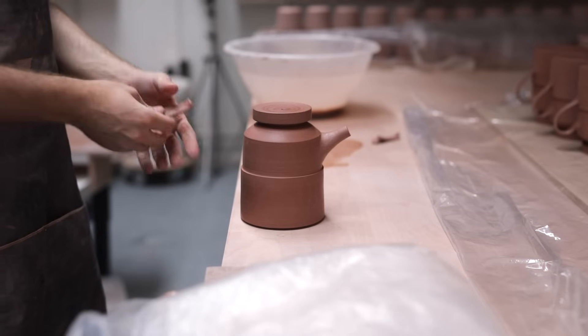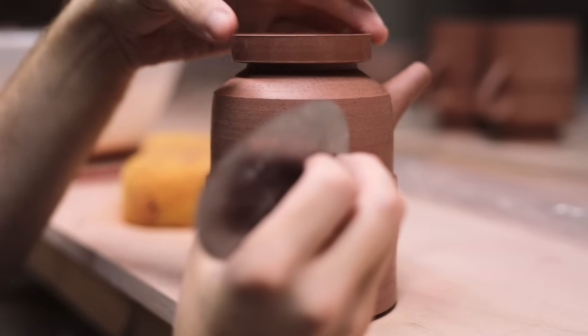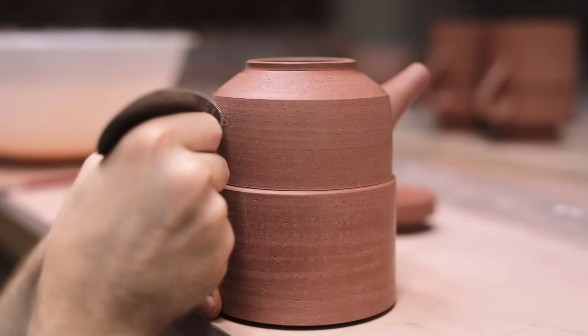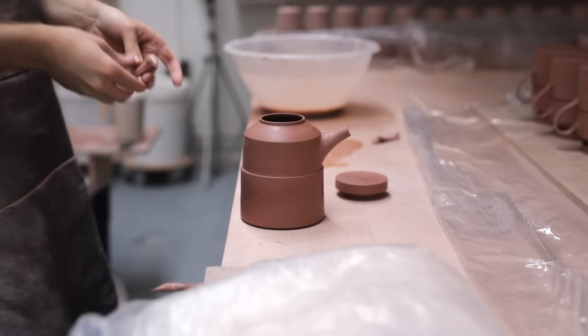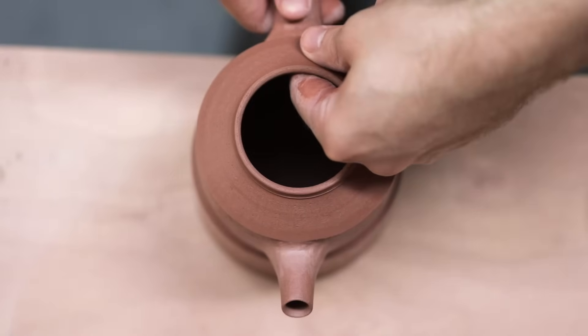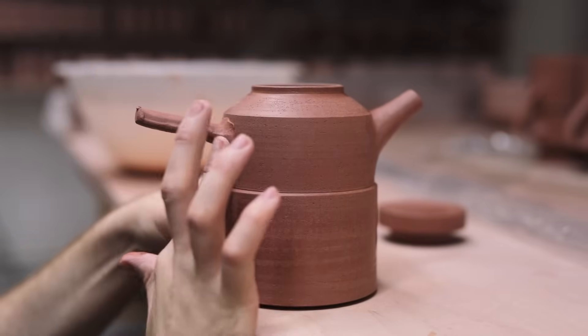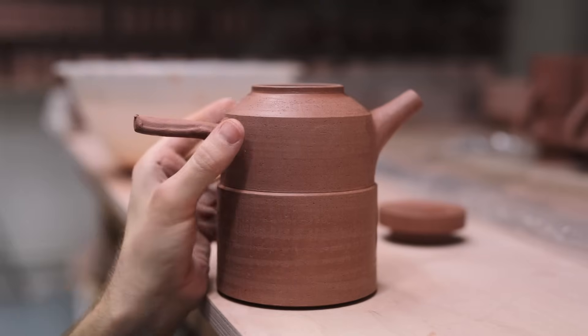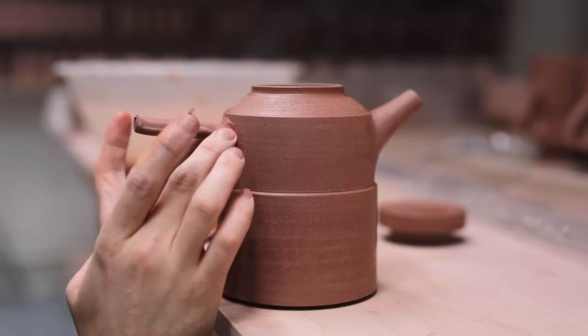So I take one of the blanks and I tap out one end. This creates a flare of clay which I'll easily be able to blend into the body of the teapot, without having to steal material from the length itself, which would create a thin spot in the join. I then use a serrated kidney to score an area that's directly opposite the spout — the two parts really need to be in line — so I crouch down and line them up, and then dab some slip onto the scored area. I then take the handle blank and really firmly push it onto the scored section, and once again there's a hand inside the vessel which braces the pressure from the inside, preventing the handle from deforming the wall as it pushes inward. I then follow up with a dry fingertip that blends in the clay from the tapped-out end of the handle all the way around. This join has to be very secure, as the next stage — when I pull it finer and thinner — can put a lot of strain on the join itself, and if it isn't done sufficiently well enough, there's a good chance the handle will just be torn away from the teapot.